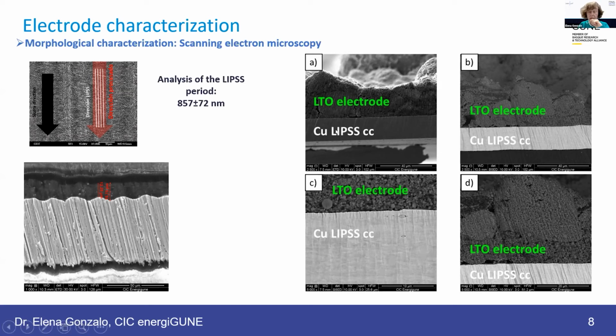And you can distinguish the copper LIPSS current collector and what is on the top, that is the LTO electrode. If you check carefully the border between the LTO and copper LIPSS, you will see that it is perfectly cast and perfectly aligned. So the adhesion between the LTO and the copper LIPSS is quite good.